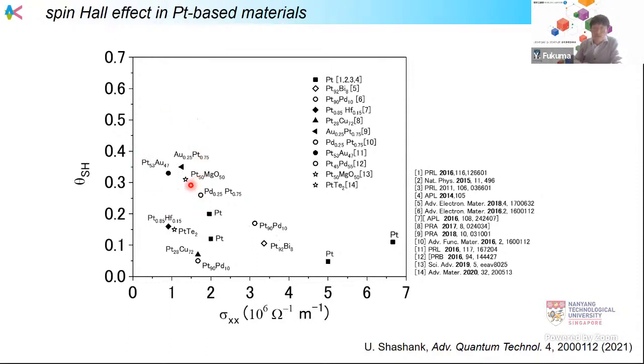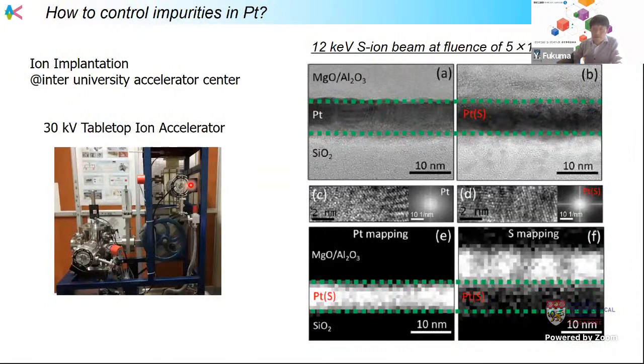We need to control the impurity in the platinum layer with good accuracy. In this sense, we use an ion implantation technique in the platinum layer. We can use this kind of very small acceleration equipment. Then we inject sulfur impurity into the platinum layer.